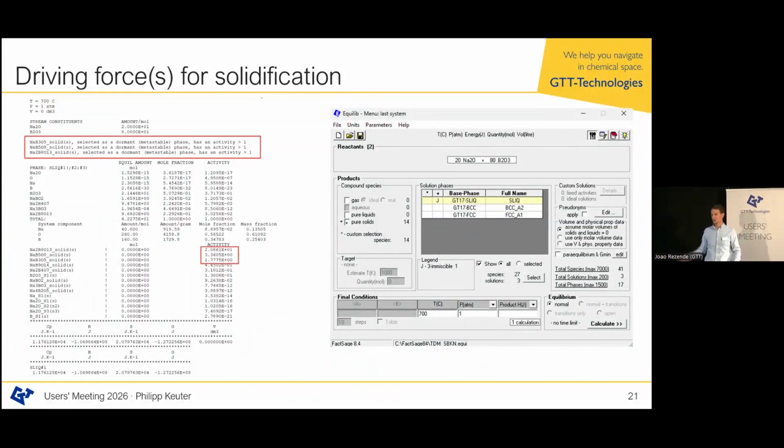These were 2 examples. One can do much more. When it comes to glass ceramic applications, for example, you could also calculate your equilibrium based on a crystalline solid and your liquid phase, and then you can calculate, for example, what the driving force is for a second solid to precipitate. That is another very interesting application example, which I will not explain, but I want you to be aware that technically the same principle applies, but it is simply a type of calculation where you add another solid phase into your equilibrium consideration.